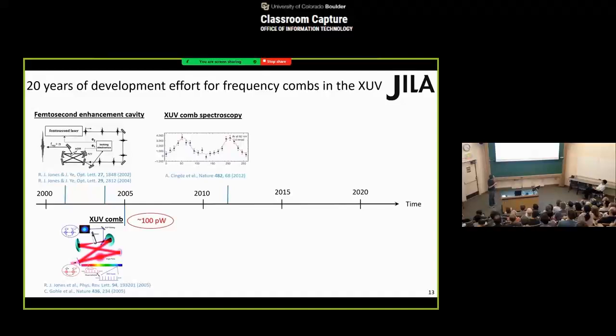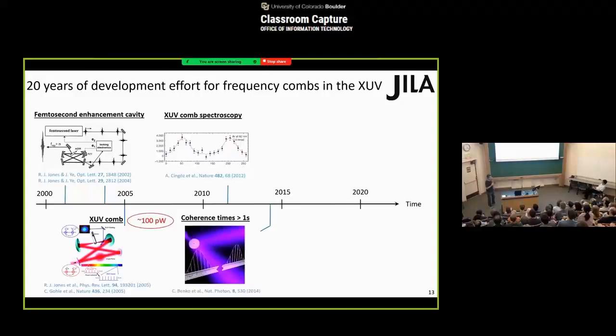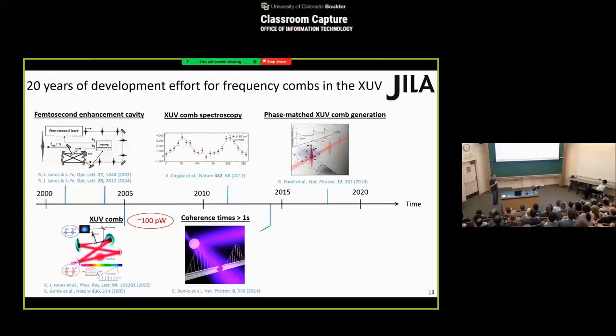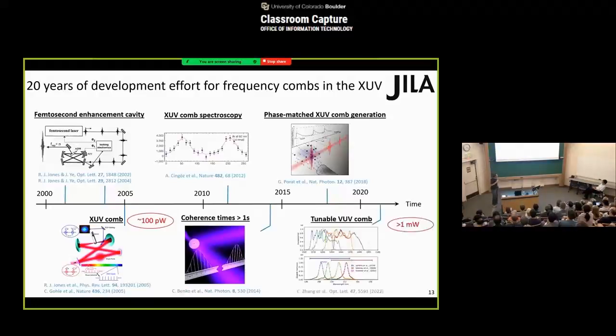We've seen that people can actually use XUV comb structure for spectroscopy at even 82 nanometers of wavelength. We've seen that we can control the phase noise in this XUV comb generation process very well, such that we get coherences longer than seconds. We've also learned how to phase match these XUV comb generations inside the enhancement cavities. So today, we're building on top of all this knowledge, and we made a tunable VUV frequency comb that's tailor-made for driving this thorium nuclear transition, with more than milliwatts of output power. So now we have a great laser source.